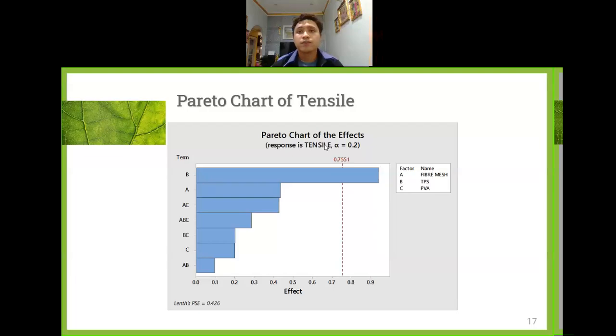Excessive use of thermoplastic can strengthen and bind between fiber and PVA to become stronger and more durable. The least significant is the mixture between fiber and TPS. From the diagram we can conclude that when we make a mixture with too much fiber and only a little combination of TPS and PVA, the material will be easily brittle and not hard enough to conduct the tensile experiment.